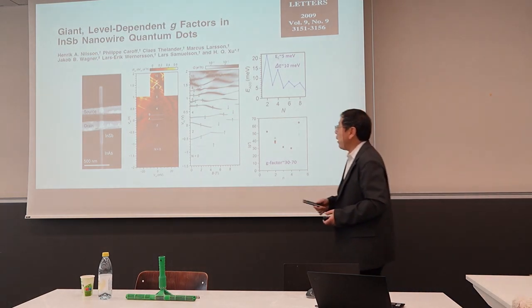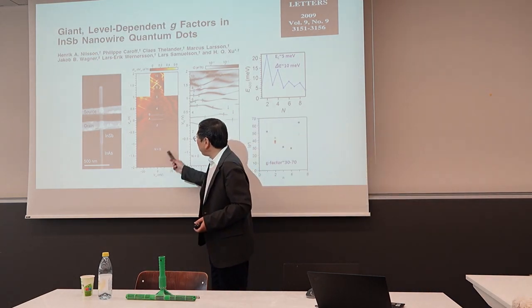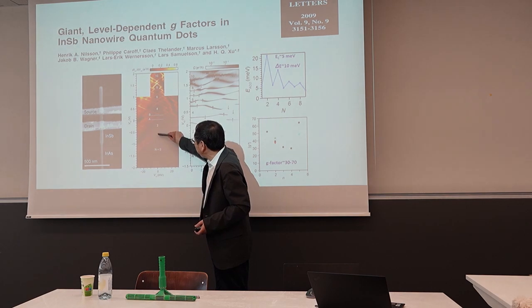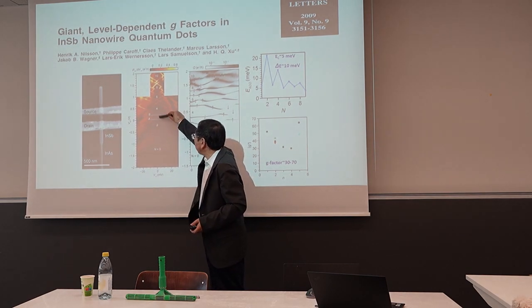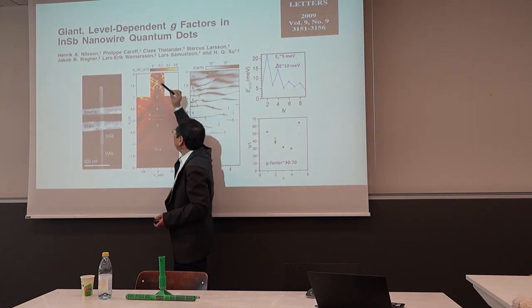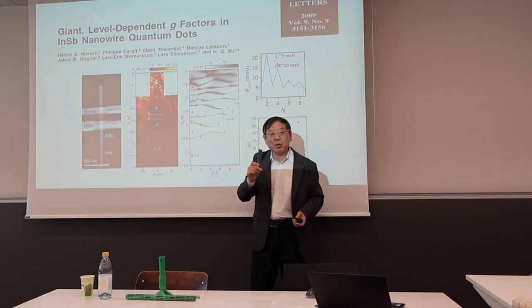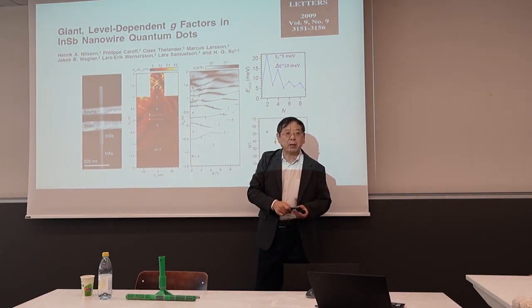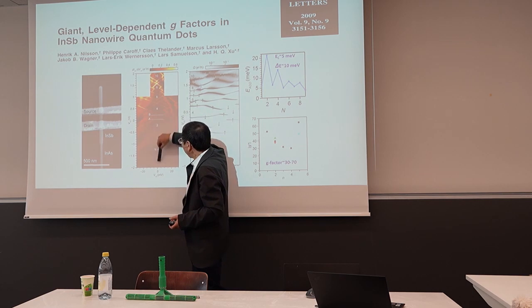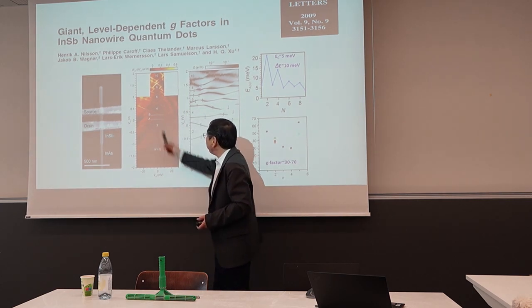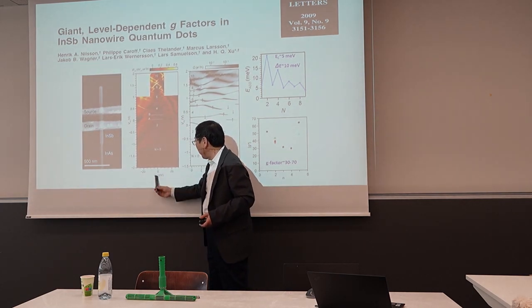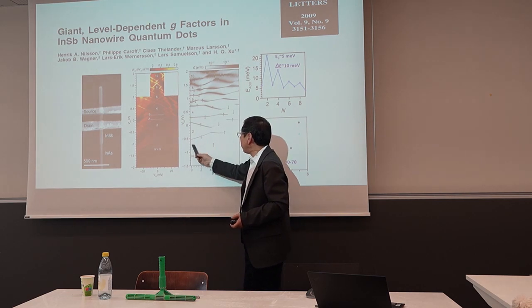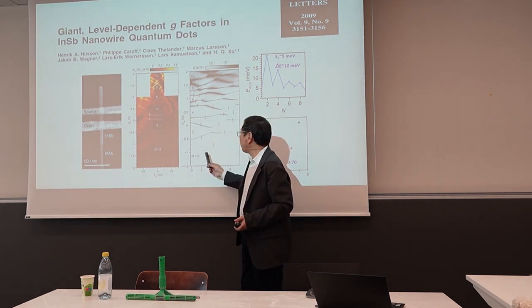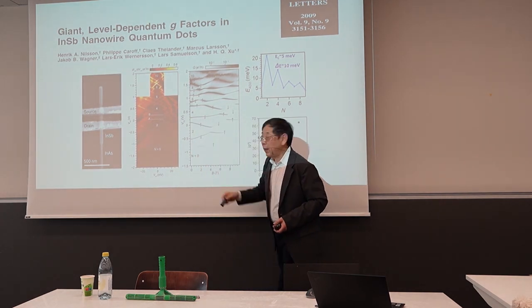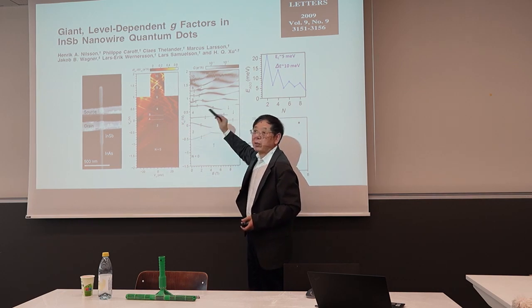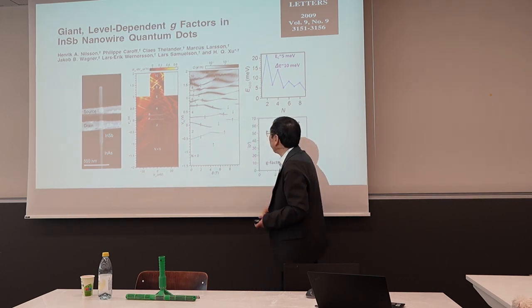This is one I showed again. So you see the Coulomb blockade effects. This is 0 electron, 1 electron, 2 electrons, and 3, 4 electrons. Here is the Kondo peak. In the Coulomb blockade regime, there's a very bright stripe at zero bias. That's the Kondo peak. And with the magnetic field, if you set up the zero bias, then as I said, this line is split. That is due to spin. And this distance is the charging energy. So you can map out a lot of things.